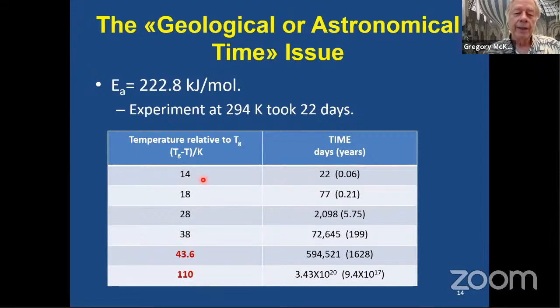So what's the time scale? In that particular set of experiments, it took us 22 days to do the first experiment to get it into equilibrium at 14 degrees below Tg. If we go to 18 degrees below Tg, it's a 77-day experiment. At 28 degrees below Tg, it's almost 6 years. At 38 degrees, it's 200 years. At 43.6, and I'll explain in a minute why we use that number, it would be 1,628 years. That's a nice number because it's sort of the lifetime people worry about when asking whether cathedral windows flow, which they don't. But look at how long the relaxation time is just 43 degrees below the glass transition with a low activation energy.